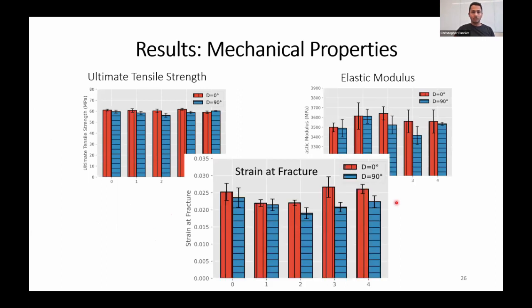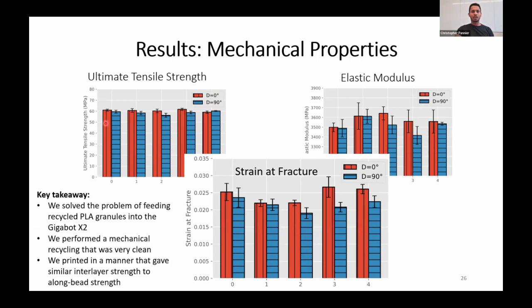So now we just put the 0 degree and 90 degree in the same figures to look at whether there is any trend, whether increasing or decreasing, in the strength, the elastic modulus, or the strain at fracture. But it seems that it's just statistical differences, and there are no major differences that can be noticed from these figures.